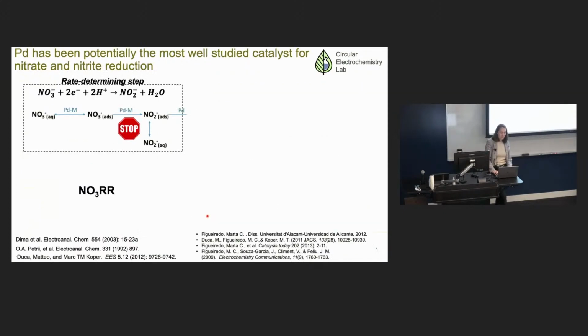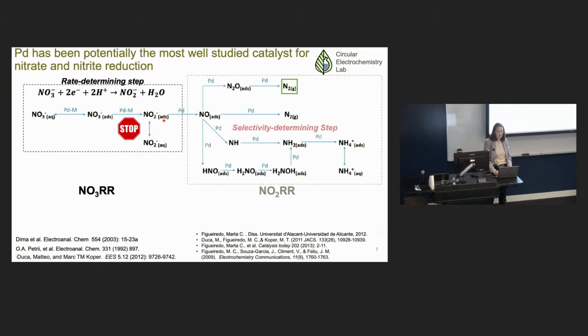Again, maybe this is too many reaction mechanisms for you, but the idea is that you have two steps. First, you need to get nitrate to adsorb to the surface. And then the second thing you need to do is you need to get nitrite to not poison the surface. Nitrite likes to actually just stay on the surface and poison the catalyst. So you need to be able to find a material that can adsorb nitrate and desorb nitrite. And then you need to have catalysts that can help you either couple your NO to get to nitrogen, or not allow NO to couple to each other so you can get to ammonia. There are lots of different materials aspects associated with designing these catalysts, because there are lots of different intermediates and different reaction pathways you could follow.